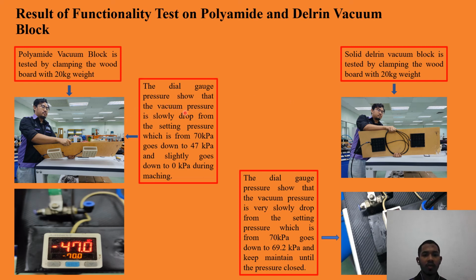The dial gauge pressure shows that for the hollow polyamide vacuum block, the vacuum pressure slowly dropped from the setting pressure, which is 70 kilopascal, down to 47 kilopascal and slightly goes down to 0 kilopascal during machining. And for the solid Delrin vacuum block, the dial gauge pressure shows that the vacuum pressure very slowly dropped from the setting pressure, from 70 kilopascal down to 69.2 kilopascal and kept maintained until the pressure was closed.